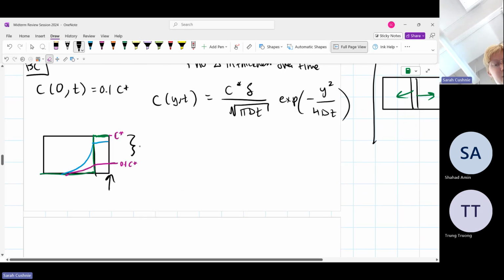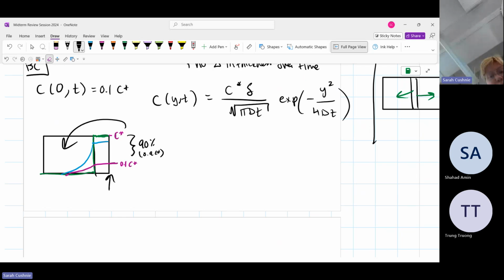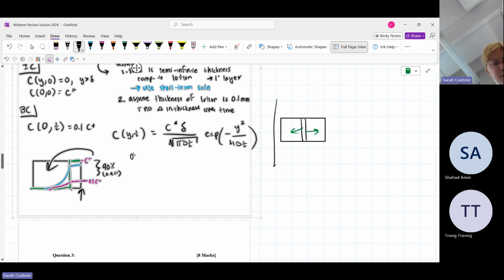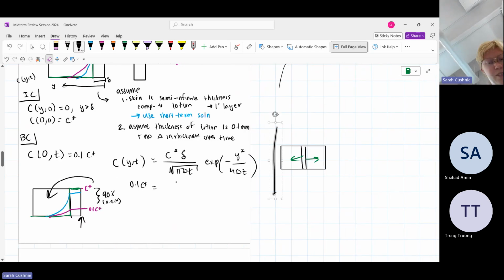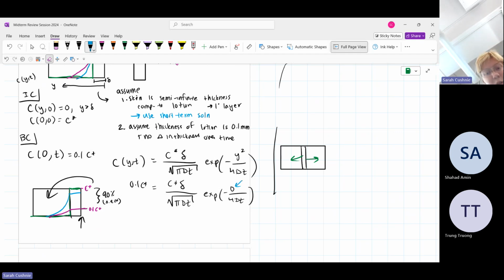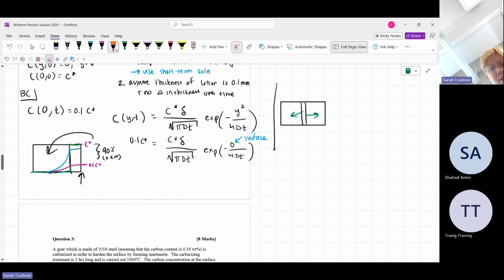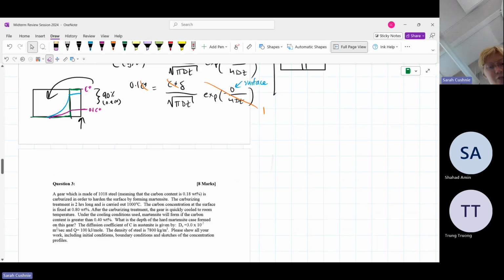And that's because 90%, or 0.9 C star, has diffused into the skin, into the bulk of the body. So we're going to set 0.1 C star equal to, and I'm going to leave it in parametric form right now, C star times delta over root pi Dt times the exponent of negative 0 over 4Dt. Remember, our y is equal to 0 because we're looking at the surface where we're applying that lotion. So we know the exponent of 0 is equal to 1, so we can cancel out the entire term, and we can cancel out the C star. So you never actually need to know what the initial concentration of the sunscreen, of the lotion, was.